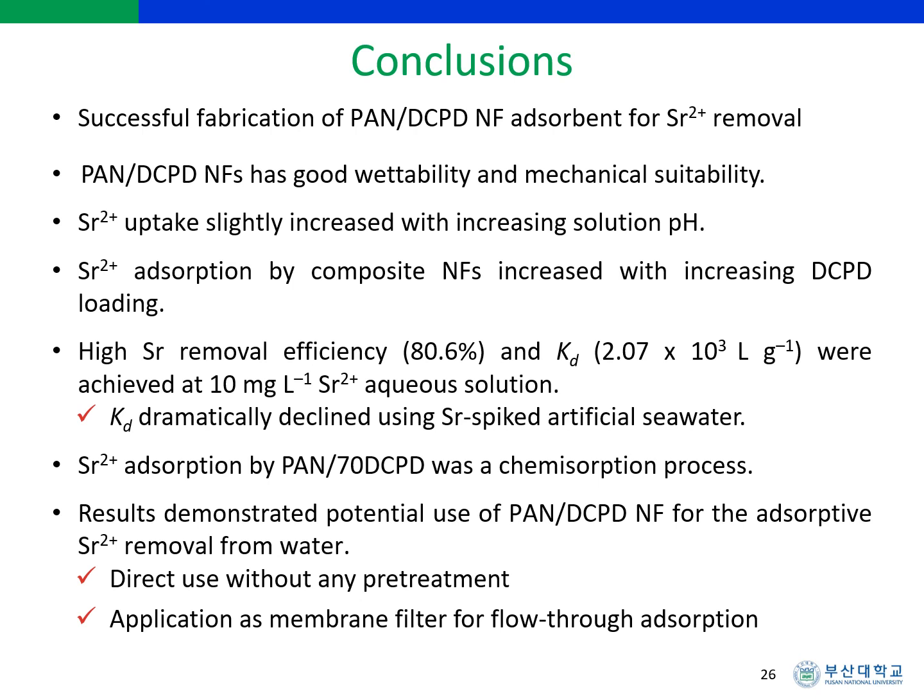High DCPD loading resulted in greater strontium uptake of the composite nanofiber adsorbent as more DCPD particles were exposed on the nanofiber surface. Strontium uptake best fitted the SIPS isotherm, indicating that strontium adsorption is a heterogeneous process. Kinetic studies revealed that strontium uptake by the composite adsorbent was a chemisorption process. The presence of competing metal ions significantly reduced the Kd of the composite adsorbent for strontium, indicating a low strontium adsorption selectivity of the adsorbent material.